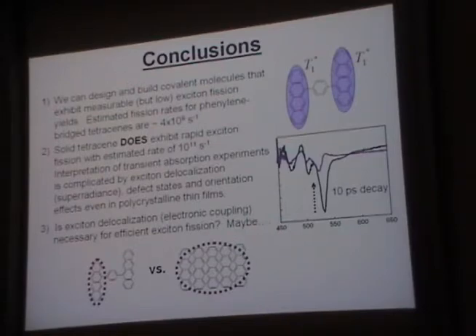But let me say something that might explain both of these. Okay, you postulate the mechanism of exciton fission. It involves charge transfer states. How do you get a low-lying charge transfer state to mix in and interact with those singlet states? It's present in the crystal, that's for sure. In fact, these are unpublished calculations from Bardeen and Spano and the whole army they have working at Georgia Tech right now. But the army says that the reason you have strong coupling in tetracene is because these low-lying charge transfer states mix in and build up your Davydov coupling. So in other words, low-lying charge transfer states make big coupling between molecules. But low-lying charge transfer states are also what you want to have that fission mechanism be operative, right? Because it involves an intermediate charge transfer state. So it may be that this makes fission possible.